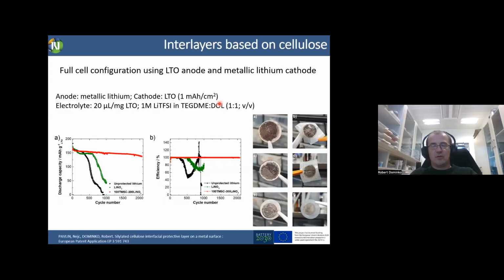Next, of course, once you have such a system, you put it against different cathode materials, and we try to test it in different environments with ether-based electrolytes and with carbonate-based electrolytes. For ether-based electrolytes, we selected lithium titanate oxide spinel structure as a cathode. It's not a real cathode, but